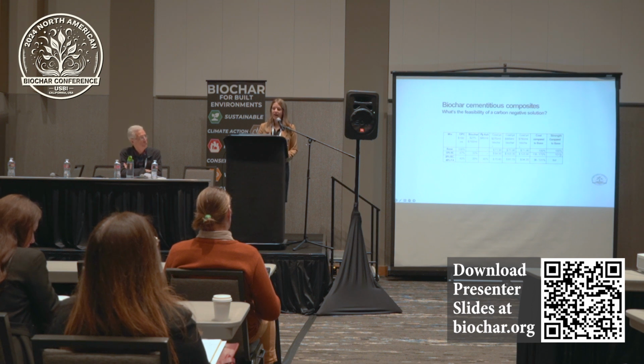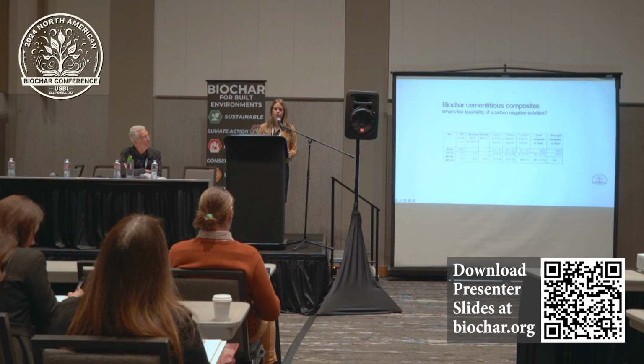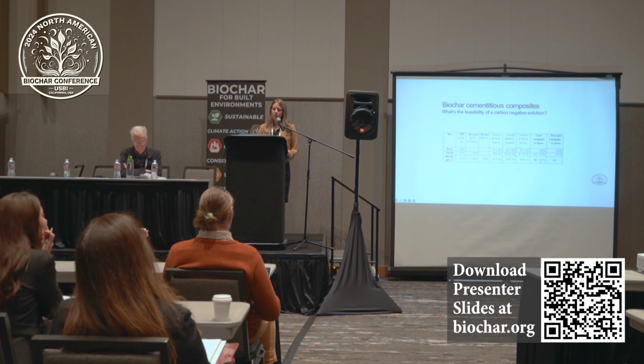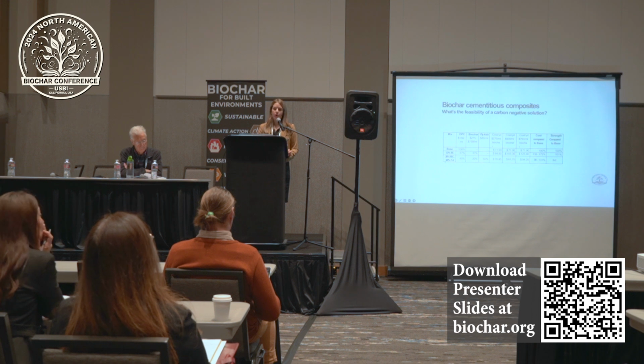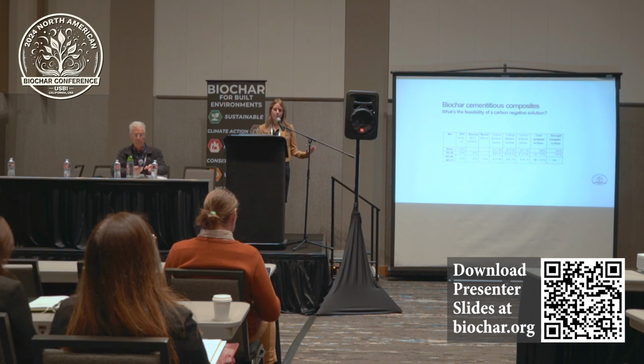And so that's great that we have a carbon neutral solution that can work, but we really need to get this number down further. And you can see what's really driving up the number is the cost of the biochar. We're also looking at other solutions. We don't have strength data on that yet, but this solution potentially would be, if we could get the cost of the biochar at this lower number, the $275 per metric ton, we could get a cost parity solution that would be carbon neutral or slightly negative, actually. So assuming that the strength comes out okay, then we've got another solution that could move forward in something cost parity for the industry. So I think this is where we really need to work together, building on our expertise from the concrete industry and the biochar industry to be able to come up with a solution that can get to carbon negativity, similar performance metrics for the concrete, and hopefully cost parity.